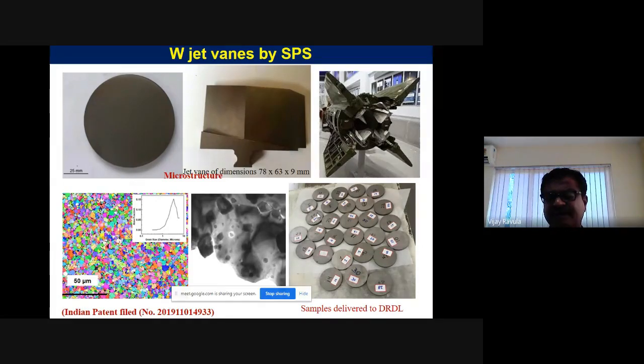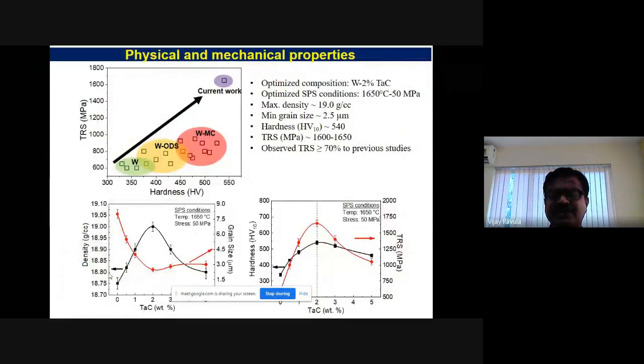DRDL, and we made around 32 pieces, in which we can even see a very fine grained structure, because we put in a nano oxide dispersed phase, a different phase we have dispersed, and that way we were able to get a very fine grained structure, and the strength values have gone up.